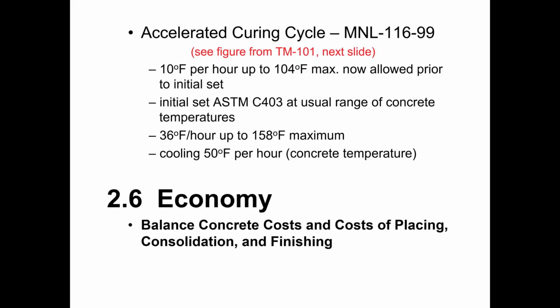In your book, on page 226, in the second paragraph from the bottom, the next to last sentence says that it must be kept less than 190 degrees. So that has been changed. The maximum concrete temperature that is allowed is 158 degrees. So if you want to mark that in your book, 158 degrees. As the book does note, there's little advantage in heating the concrete much above 150 degrees. So in recognition of that, and research that has shown that we can actually adversely affect the long-term durability of the concrete by heating it much above 150 degrees, they went ahead and lowered the maximum allowable temperature to 158. So that's where that came from.